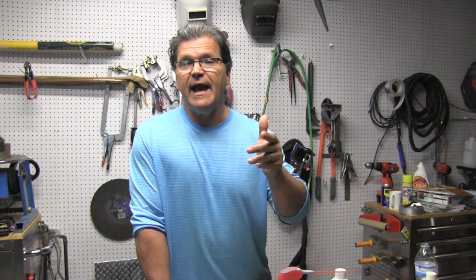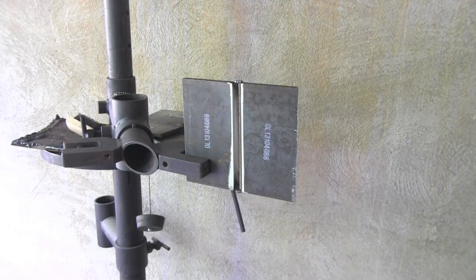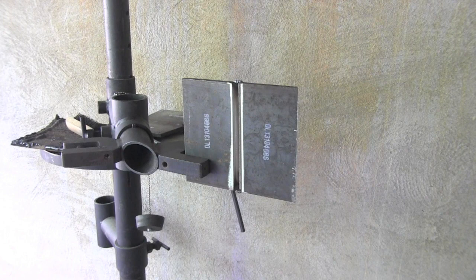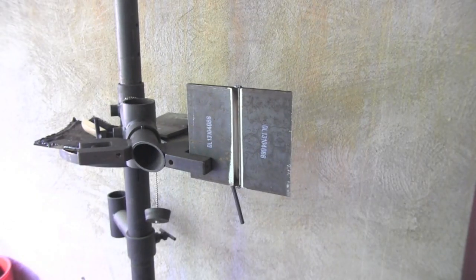In fact, I'm working on a 3G plate test video where I short circuit MIG weld downhill root, and fill and cap uphill. Here's a quick peek at the downhill root on that. Here are the specs on this joint real quickly. It's 3/8 of an inch thick, that's roughly 9.5 millimeters. 37.5 degree bevels for a 75 degree included angle. Clean to bright metal, and it's got a 1/8 to 3/32 gap and a slight land on it.